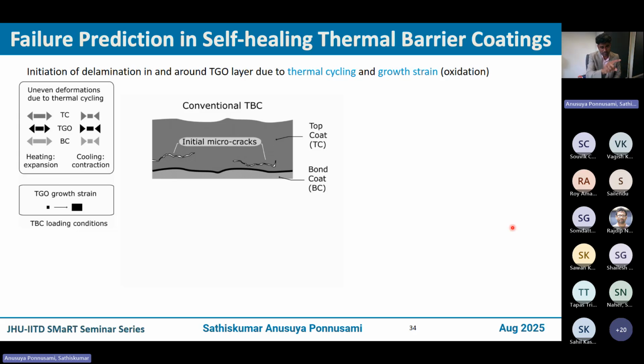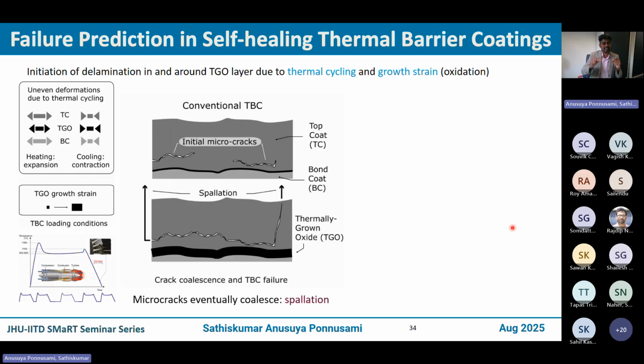But if you look at the thin black interface layer that you see, that particular layer keeps growing during operation. It is an active layer. There is another rich physics there, driven by chemical processes; a diffusion reaction process is happening there. That adds material growth induced strains and hence stresses, and hence crack evolution.